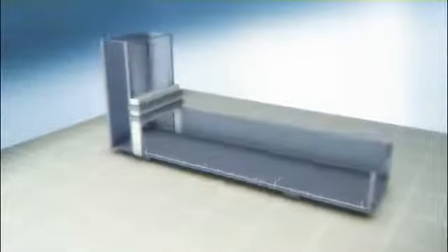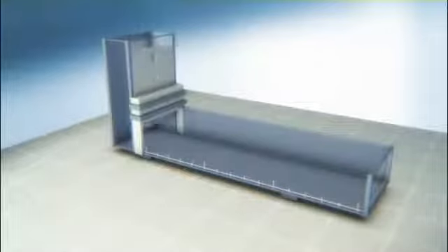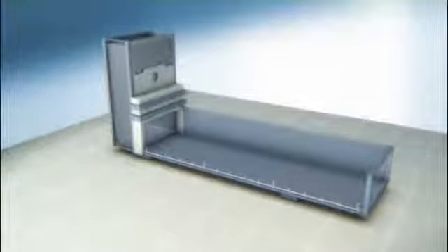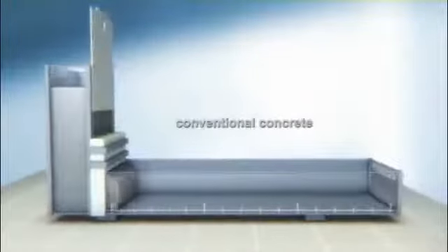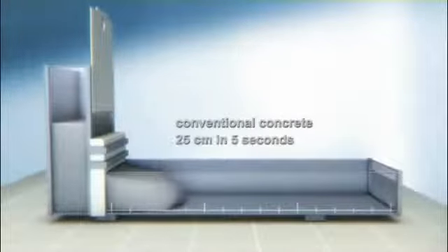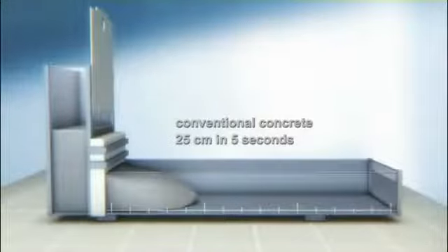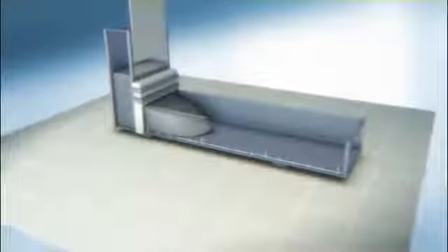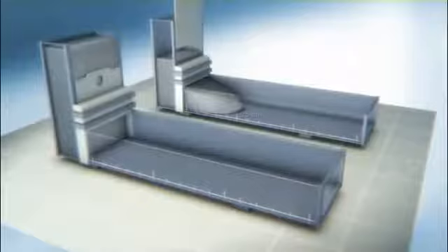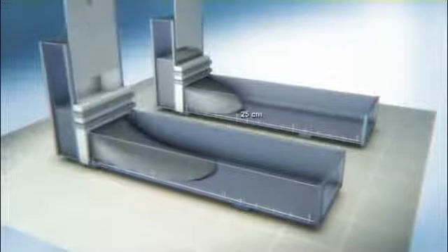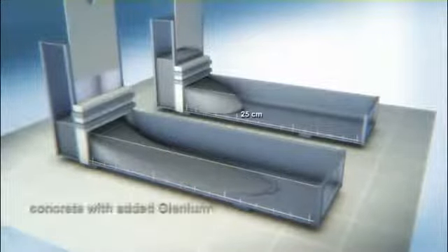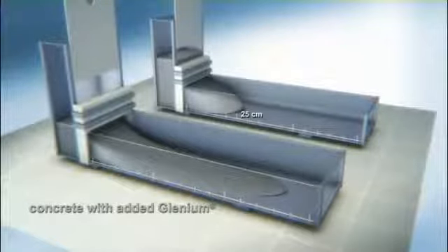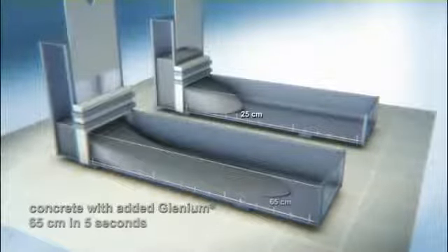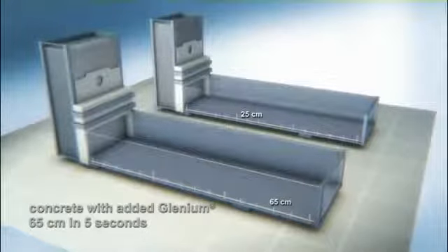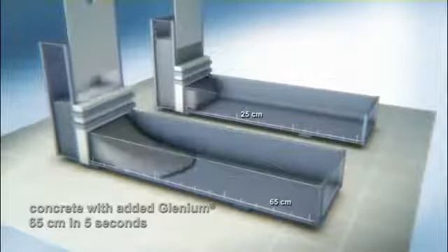A pilot plant comparative study between conventional concrete and concrete with added Glenium, but with the same water content and mixing ratio, clearly shows this. With conventional concrete, the flow process already stops after 5 seconds and after a distance of about 25 centimeters. Concrete to which the superplasticizer Glenium was added flows much faster, and the distance traveled over the same period is about 65 centimeters.